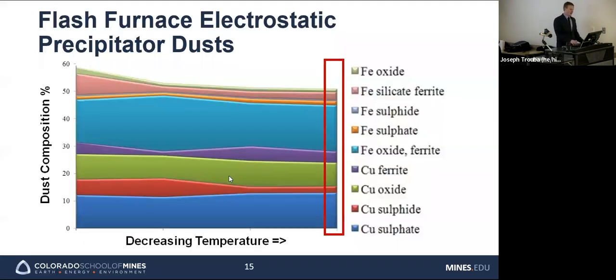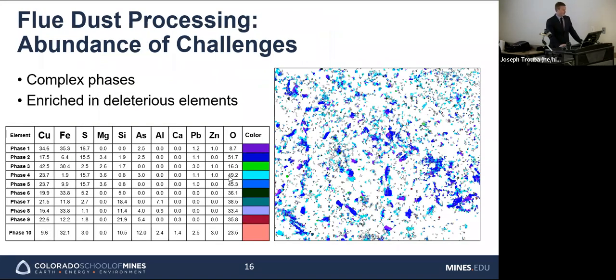So I'm focusing on the electrostatic precipitator dust. This graph here shows how the different phases change throughout the waste heat boiler, and they continue to oxidize in this environment. What leaves the waste heat boiler is approximately what enters the ESP. And you can see from these phases that it should be relatively simple. Unfortunately, it's not. This image in the bottom left shows numerous different elements present, and don't try to read the table. The point is there are numerous non-stoichiometric phases that contain various elements, making it a challenging material to process. The image here, most of you are probably familiar with automated mineralogy. The average particle size is roughly equivalent to that of a red blood cell. So it's a very fine particle.